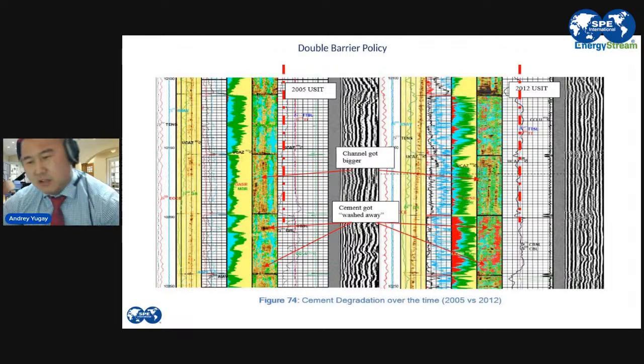Now, degradation of secondary barrier. We are still talking about degradation of secondary barrier, yeah? How confident we can say that our secondary barrier are still okay? Cement also can get degraded. Recently, I had a kind of small argue with one guy in LinkedIn who says, no, cement doesn't change. Cement is quite elastic, plastic. It's just what we see is debonding. For me, honestly speaking, the main function of cement is hydraulic isolation. So if it cannot provide hydraulic isolation, whether it's debonding or micro-cracking or microannular, I mean, I don't care, correct? If it degrades, it degrades, whether it's cement or debonded.